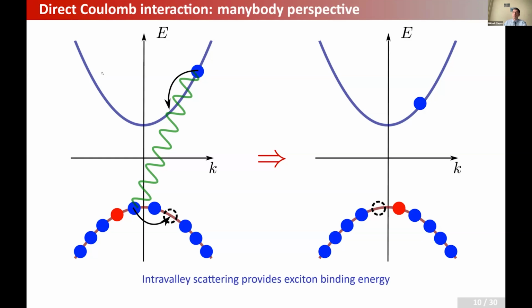It's easy. There are no occupied states. And the electron in the valence band actually goes to the only possible empty state that can be attributed to the motion of the valence band hole. And in the case of transition metal dichalcogenides, this process is related to the intra-valley scattering because both electrons stay in the same valley, and it is the main contribution to the exciton binding energy.